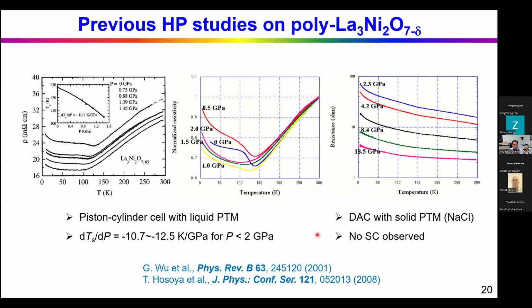Previously, there were some old papers reporting high pressure studies on the polycrystalline 3-2-7 phase. So I can find these two papers. In one, at the lower pressure, they used the piston cylinder cell with liquid pressure medium. They found that the density wave transition can be suppressed by pressure, decreasing about 10 Kelvin per gigapascal. But the previous measurement is only limited to 2 GPa for the piston cylinder.